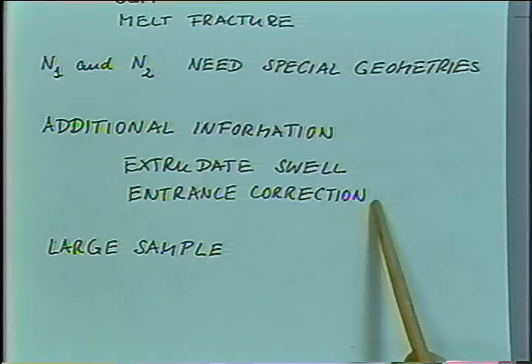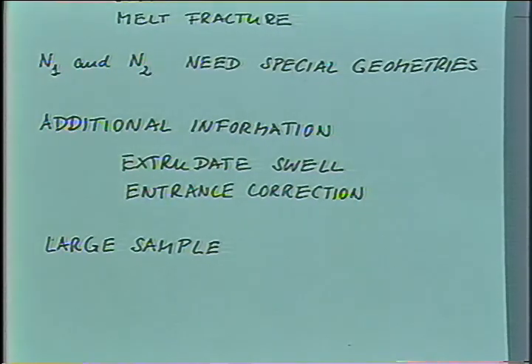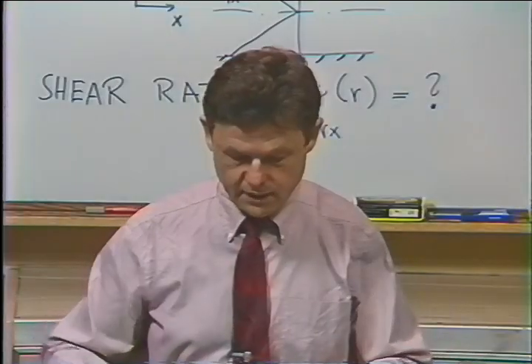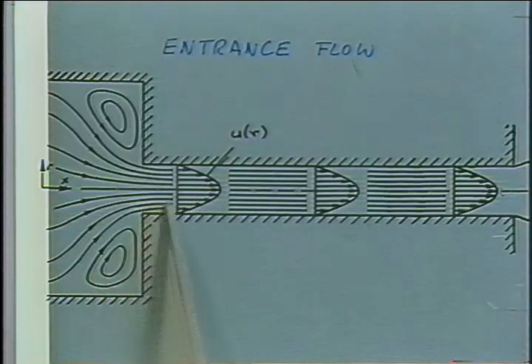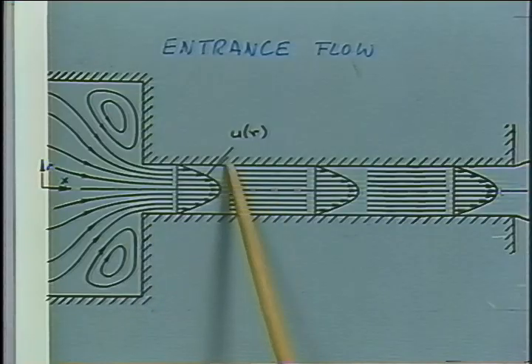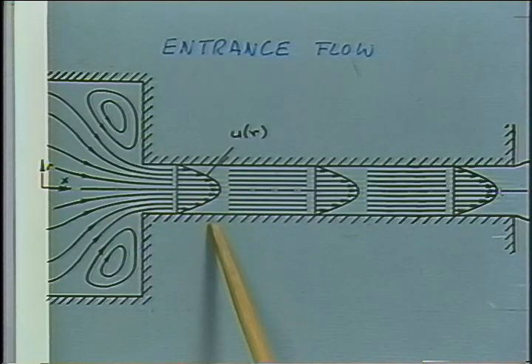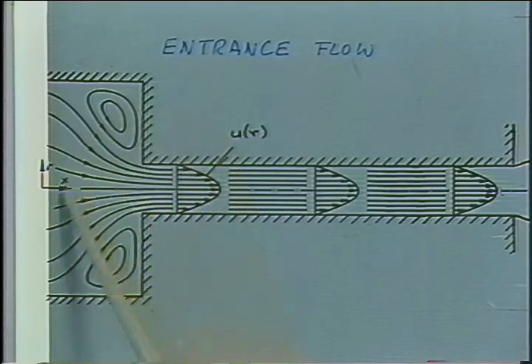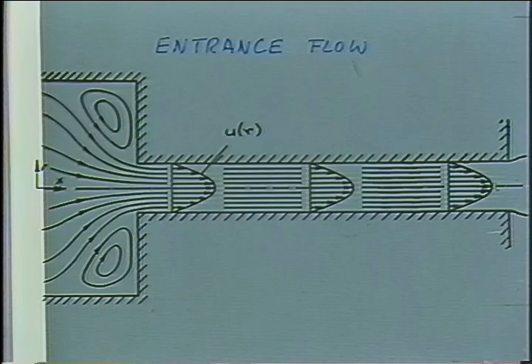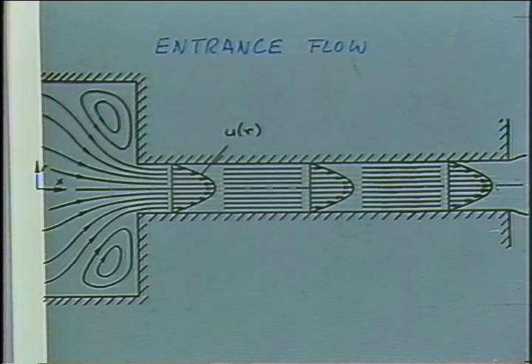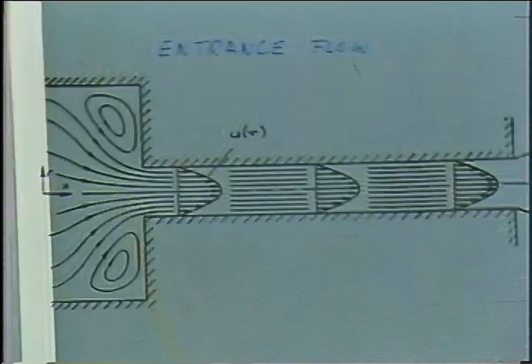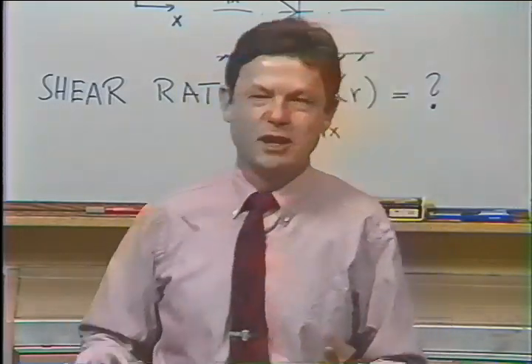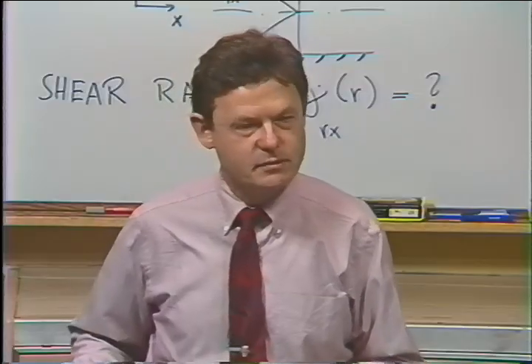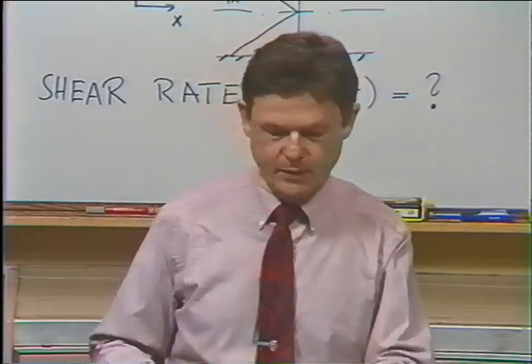Also, the entrance correction for flow into the capillary. This is the pressure drop associated with this type of flow. From the reservoir, the liquid is pushed into the capillary, it's accelerated, and it's subjected to stretching in addition to the shearing. So that type of complicated deformation probes your material in a fashion which is very different from the steady shear flow. So it's worthwhile to determine that even if the flow is too complicated to determine specific material functions from that. But it's still very helpful information.